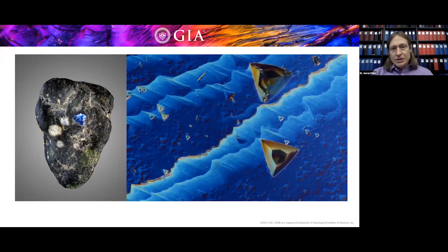Essentially, we illuminate the surface of the stone with polarized light, and then pass it through a prism which separates it and creates these interference colors, which are determined based on the distance from the point in the surface to the observer. It's a way of highlighting surface features and topography on the surface of stones with color. What you see in this photo is actual true color of what you see when you look through the oculars of the microscope. These are not false colored images.